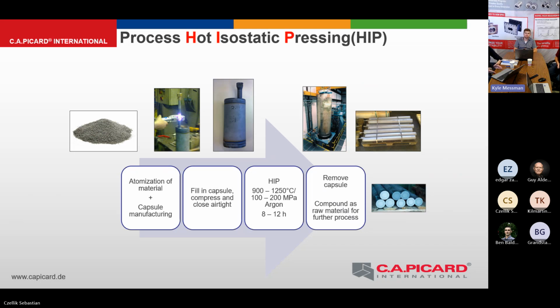And what is done? We are starting with making a very high alloyed steel, and then the steel is made into a powder by atomization. This means that we cool it very rapidly, make it into powder, and every powder grain has all the alloying elements in it. Due to that, you are able to make very high alloyed steel, which normally could only be cast. Afterwards, you have this powder, where every grain has a similar alloying content, and you put it into a capsule. You fill this capsule, the powder has to be compressed, and the capsule has to be enclosed airtight, which is a lot of know-how from the HIP steel suppliers.